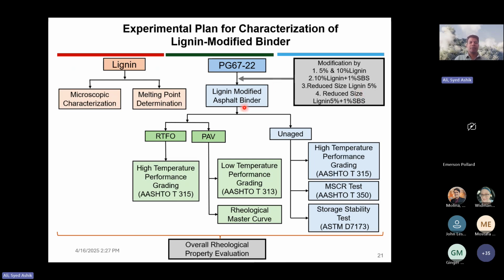Okay, so we have developed a testing protocol to mix lignin with asphalt binder, and I'm going to show you in our next slide how we did it. And when that product is ready, we use the unaged lignin modified binder, and we evaluated the high temperature performance grade using dynamic shear rheometer or DSR testing. We conducted MSCR test, multiple stress creep recovery, and also conducted a storage stability test on the modified binder.